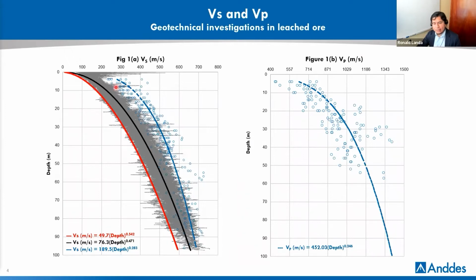The Vs and Vp measurements are shown here. Figure 1A depicts the estimated and measured Vs profiles in grade. We have presented the estimates of Vs as per the correlation proposed by Robertson, Felton and I, as a function of the CPT tip resistance. And in blue, the measurements themselves by the SCPTU geophones.